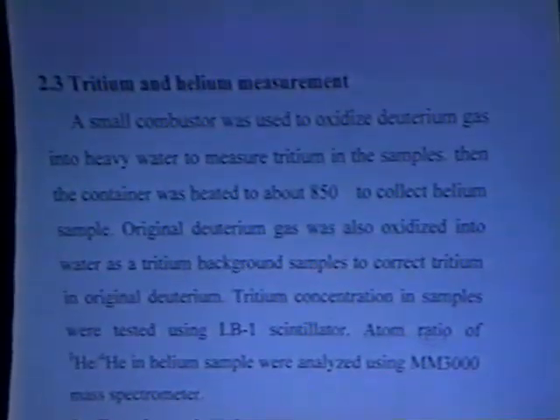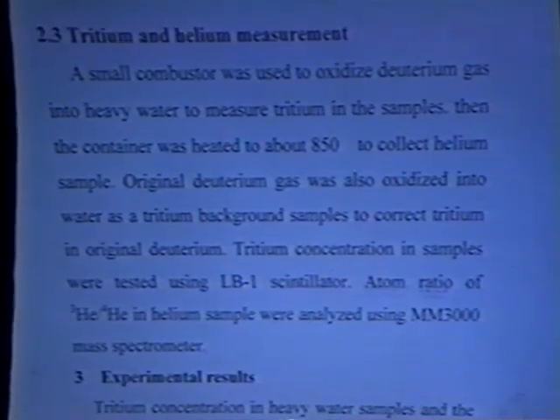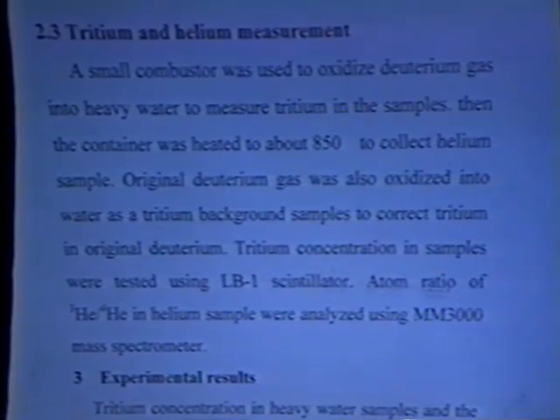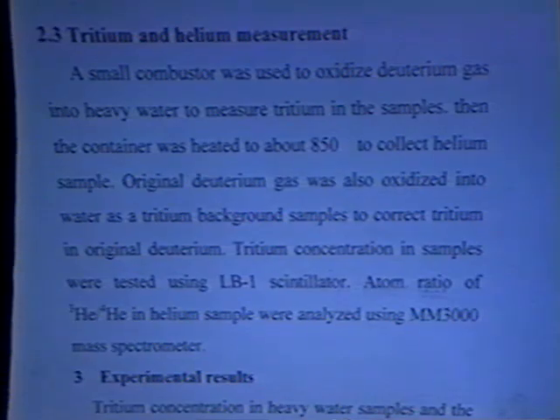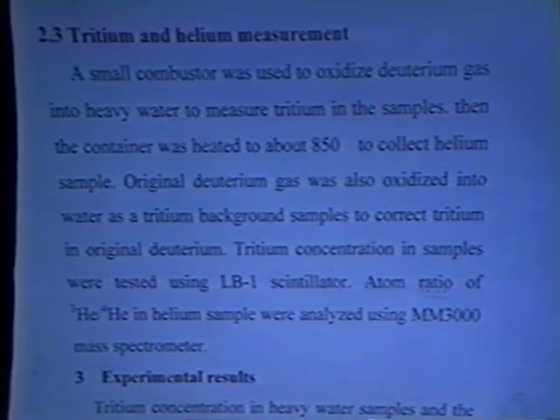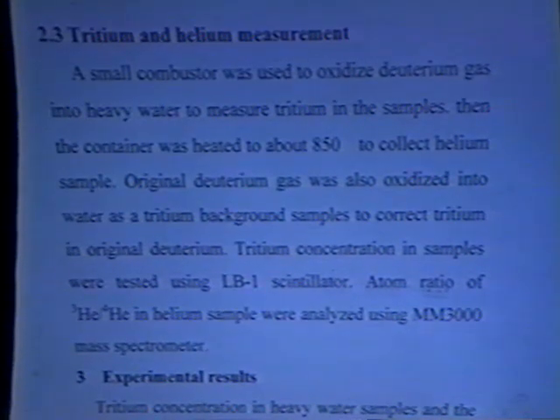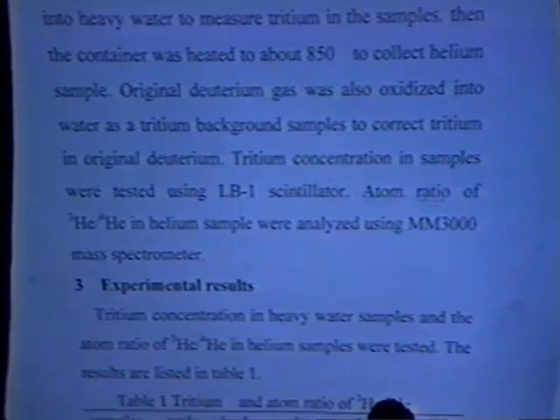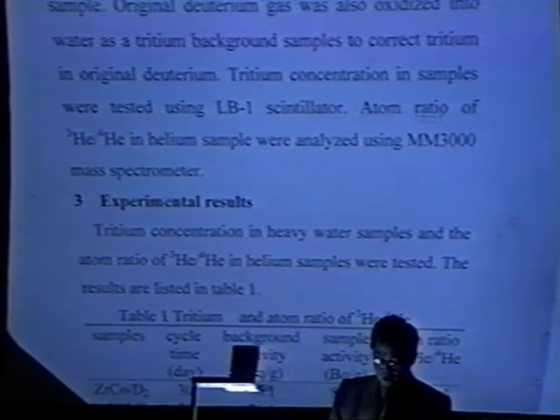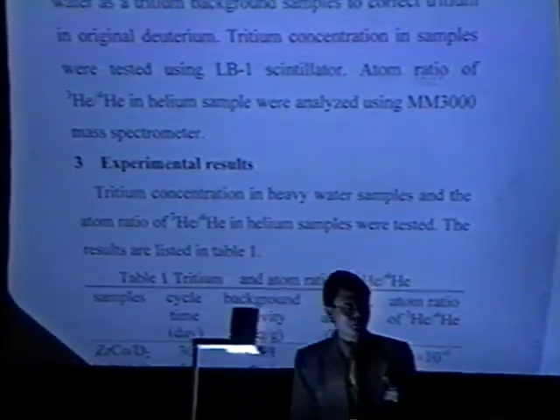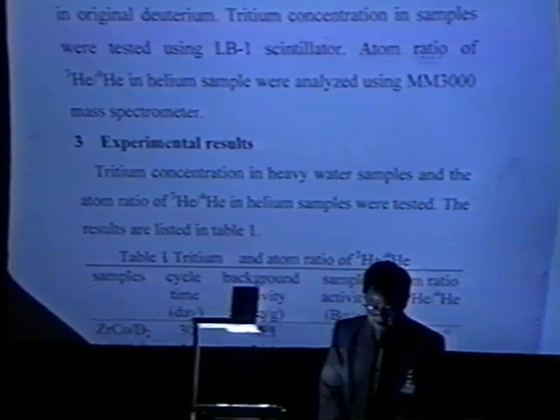Third, tritium and helium measurement. After temperature cycling of these containers, a small combustor was used to oxidize deuterium gas from the containers into heavy water to measure tritium concentration in the samples. Then the container was heated to about 850 degrees centigrade to collect helium samples. Original deuterium gas was also oxidized into water as a tritium background to determine the tritium in the original gas.